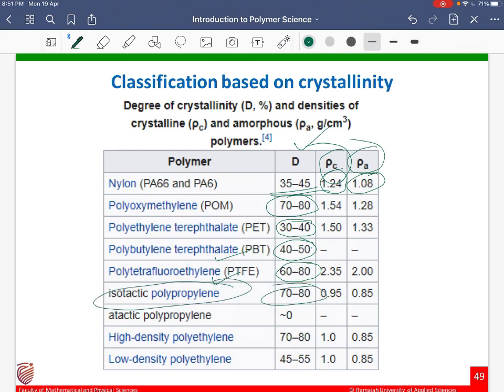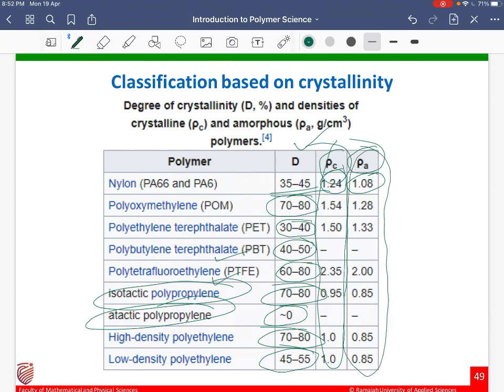Isotactic polypropylene 70 to 80, crystalline polymer. Atactic polypropylene, because there is no regular arrangement of the side groups. It doesn't follow any kind of regular arrangement when you cool the molten form of atactic polypropylene. It doesn't have any crystalline region or crystallinity, so it's an amorphous polymer. High density polyethylene 70 to 80 crystalline, low density polyethylene 45 to 55, it's showing semi-crystalline nature. And we can see that the density of the crystalline region will always be higher than the density of the amorphous region.